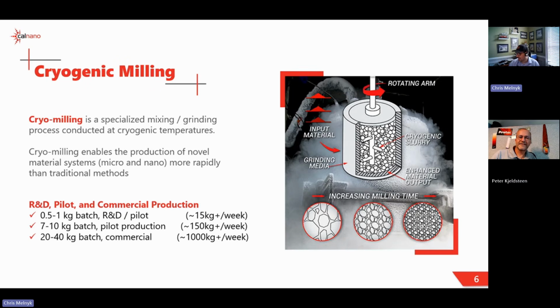So here's the basic setup. Obviously it's an illustration, but we have a vertical shaft, in our case, with an arm in it and a very high amount of torque and rotational energy being imparted into a vessel that is full of grinding media. Now that could be tungsten carbide, it could be stainless steel. Typically, we just use hardened stainless steel. It's a good workhorse for all this.